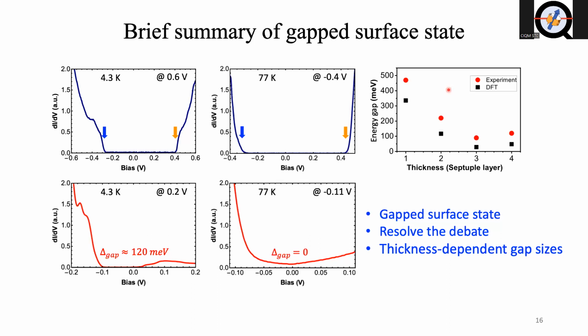I'm sorry, could you repeat the question for the people on Zoom? Okay, sure. The question is, do we have temperature dependent data points between 4.3 Kelvin and 77 Kelvin? And the answer is no. Unfortunately, we don't have them, because of the limitation of our instrument, we can be at either liquid helium temperature or liquid nitrogen temperature. But the side note is we have characterized the Néel temperature for our sample, which is 25 Kelvin. It has some variation from sample to sample, but the Néel temperature is consistent with what has been reported in the literature.